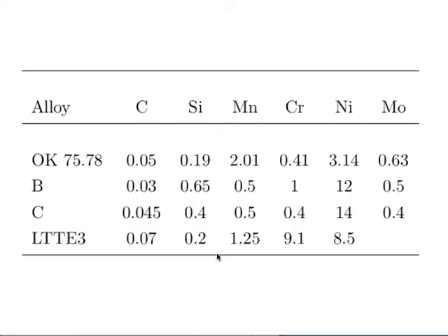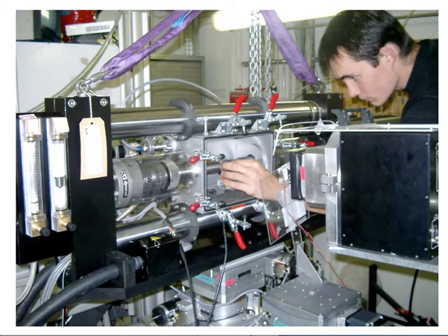So here, for example, is an alloy with that much chromium, that much nickel, manganese low, and very little carbon, right? Because we are going to form martensite, but we want the martensite to have good properties. And Olbry and Jones' experiment was very simple. They took a tensile specimen, constrained it, and allowed it to cool.